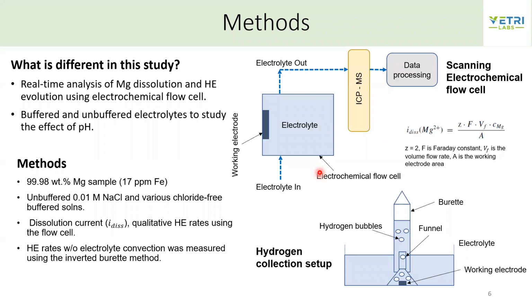Called atomic emission spectroelectrochemistry. What this does is we have a working electrode connected to the potentiostat depending on the reaction you'd like to perform. We have electrolyte which flows inside the electrochemical cell, pops out, and is delivered to a mass spectrometer, where the chemistry of the electrolyte that comes out is investigated. Then, depending on the process data, we can calculate the dissolution current of the Mg2+ based on Faraday's law. This is called a scanning electrochemical flow cell in this study.